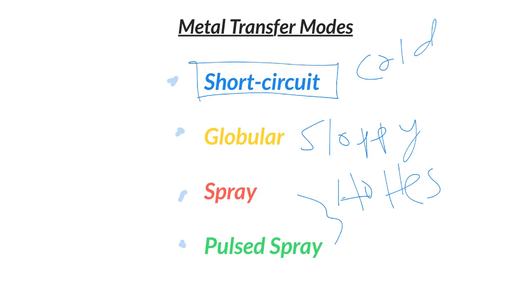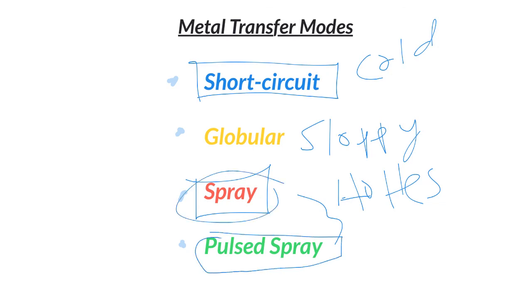It's all position welding. You can make some really nice beads, you know, stacking dimes. And then you have spray, which sprays it in like butter, literally, like it says. But it's hotter. We're limited in our positions. And really, pulse spray allows us to do the exact same thing, except for multiple positions like our short circuit. So it's kind of the ultimate metal transfer mode for MIG. The problem is, does your machine have a pulse mode? And if not, it's probably going to cost you a little bit more to get one of the machines that actually has that as an option. Awesome. If you get a chance to use it, you can spray metal literally vertical, overhead, and anything else that you can imagine.